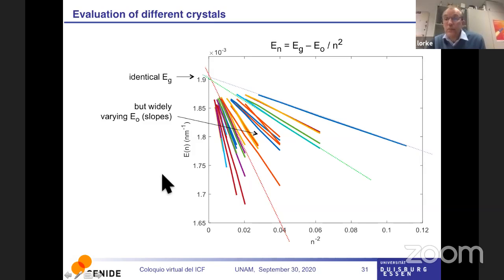Because as nicely as it fits with the Rydberg series, one puzzle is that each of these straight lines has a different slope. So each of them has a different E0, a different Rydberg constant. Now we know that the Rydberg constant is dependent on epsilon, on the dielectric environment, and it's also dependent on the effective mass. So in one material you have a different Rydberg than in another. But here this is all the same material, and each crystal has a very, very distinct E0.